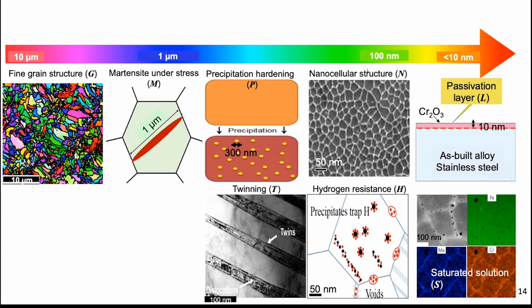But always when you produce an alloy that is very strong, there is a problem called hydrogen embrittlement. So we can tailor the formation of precipitates to prevent the embrittlement due to hydrogen.